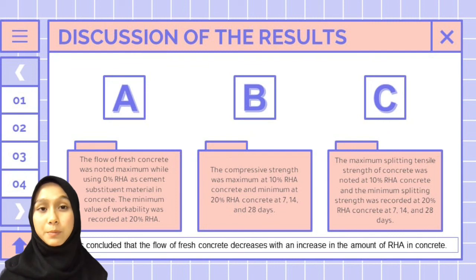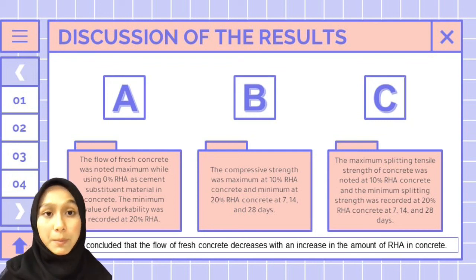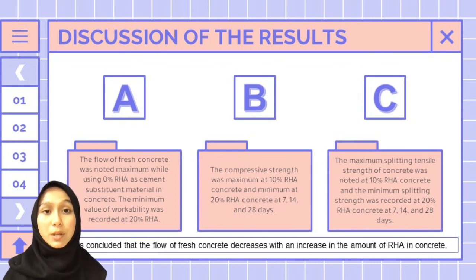For the first experiment, the flow of fresh concrete was noted maximum while using 0% RHA as cement substituent material in the concrete. The minimum value of the workability was recorded at 20% RHA. The second experiment is the compressive strength test, which was the maximum at 10% RHA concrete and the minimum at 20% RHA concrete at 7, 14 and 28 days.